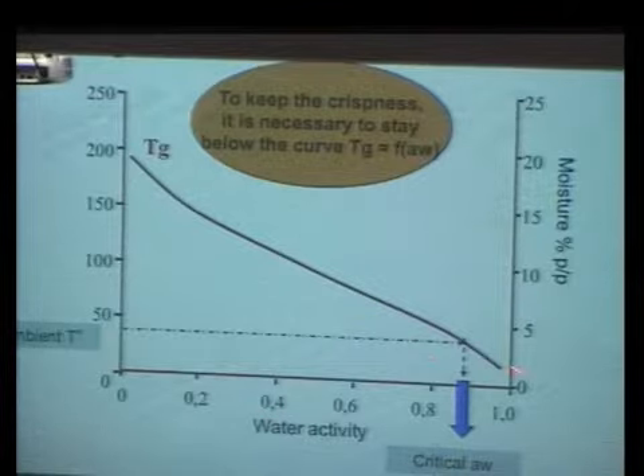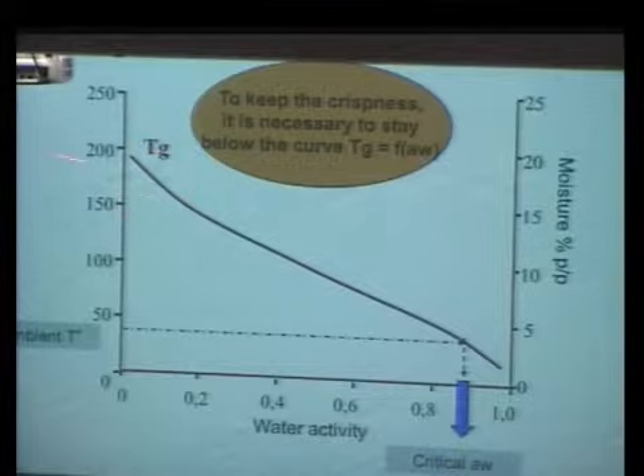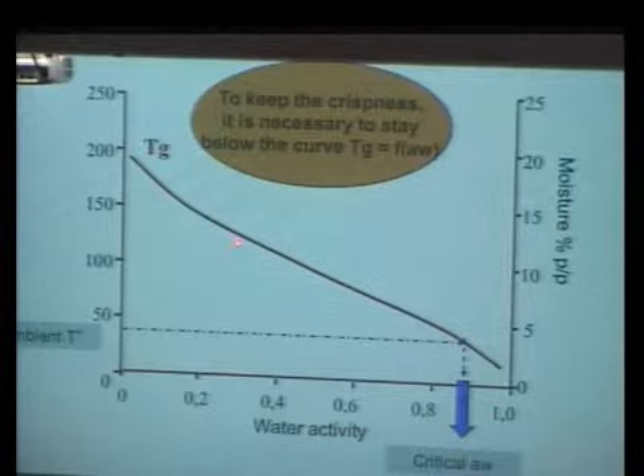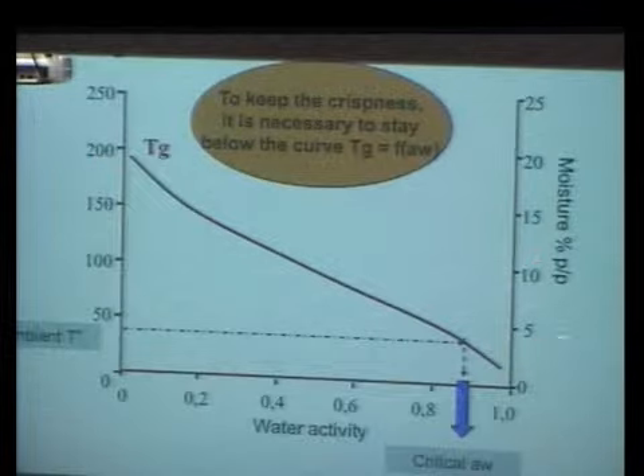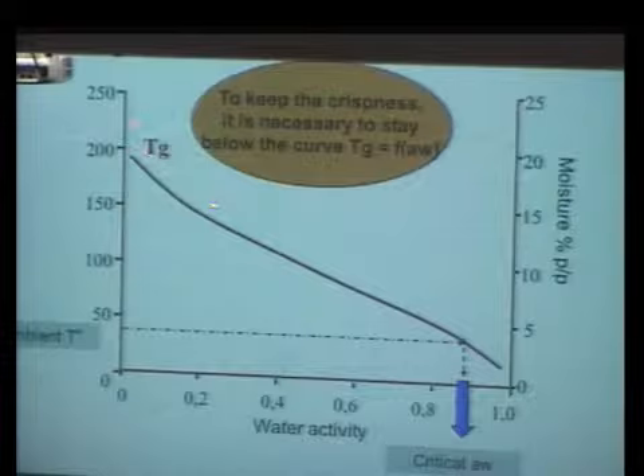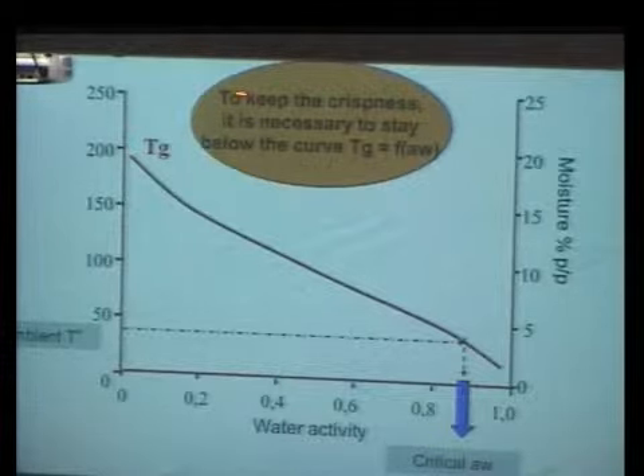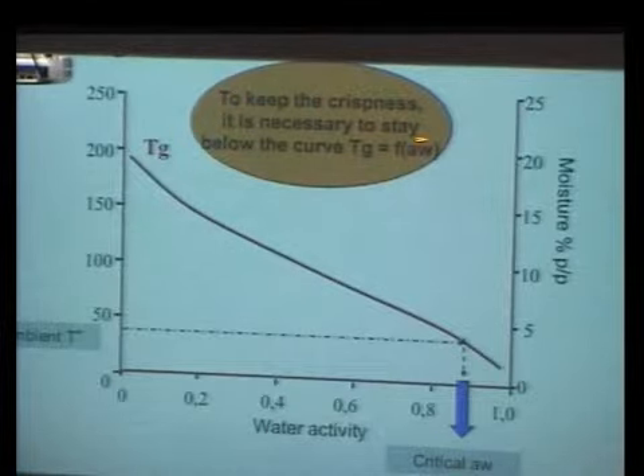It is this curve. You can see when the gluten is quite dry, only dry, the temperature of its glass transition is very high, 200 degrees. And when the water activity increases, meaning the moisture of the product also increases, there is a strong decrease of the glass transition. So what we know is that the crispness of your biscuit